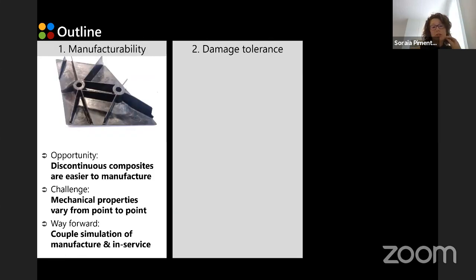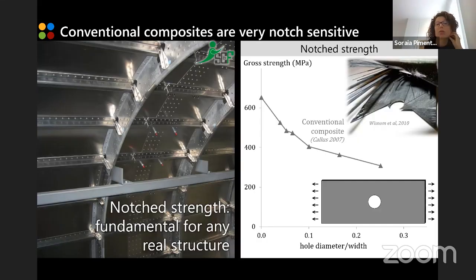So moving now from manufacturability into damage tolerance. One problem that we have with conventional composites is the fact that they are very sensitive to notches. So as I mentioned previously, as soon as you put a hole in the conventional composite, you are basically breaking the continuity of the fibers, and that means that you create a very weak spot locally. And this becomes very problematic when you think about real life structures. So on the left-hand side, I'm showing the fuselage of an aircraft, and you can see that basically the structure is full of notches.